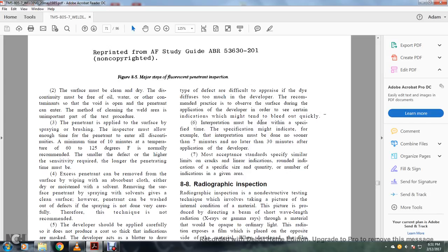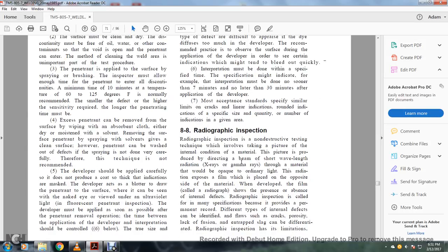6. Interpretation must be done within a specified time. The specification must indicate, for example, that interpretation must be done no sooner than 7 minutes and no later than 30 minutes after the application of the developer. 7. Most acceptance standards specify limits on cracks and linear indications, rounded indications of a specific size, and the quantity and number of indications in a given area.